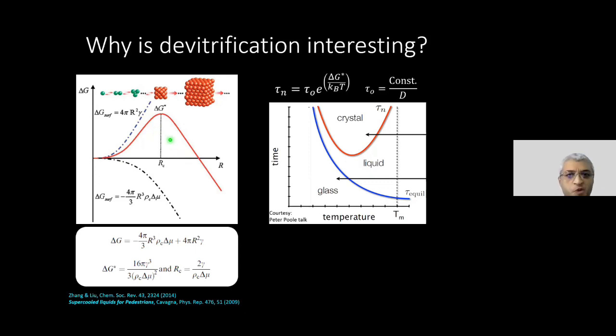Now you know from your experience of putting a liquid in your refrigerator that the cooler the freezer, the faster you tend to get an ice crystal to form, right? But that is not always the case. The reason is the nucleation time, the time it takes to form the first nucleus, which goes as so. And now this delta G star has this delta mu in the denominator. What it means is that as you start cooling the sample more and more, although the thermodynamic driving force is becoming larger and larger, you're also providing less and less energy in terms of kBT to cross the barrier. On top of that, you also have this prefactor tau naught, which is some constant that I won't go into, divided by the diffusivity of the particle in a dilute liquid. So this tau n is essentially going to be a non-monotonic function of temperature.